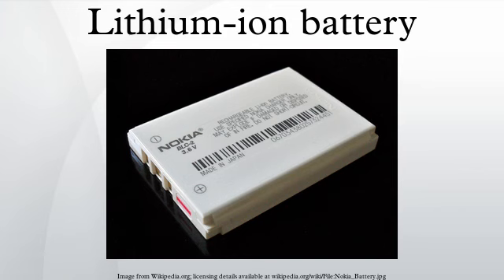In 1985, Akira Yoshino assembled a prototype cell using carbonaceous material into which lithium ions could be inserted as one electrode, and lithium cobalt oxide, LiCoO2, which is stable in air, as the other. By using materials without metallic lithium, safety was dramatically improved. LiCoO2 enabled industrial-scale production and represents the birth of the current lithium-ion battery.